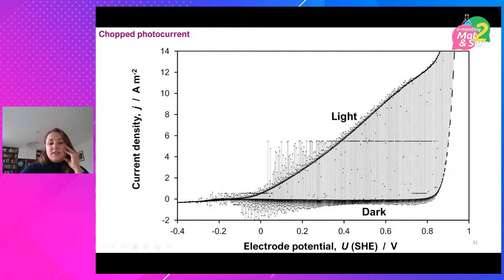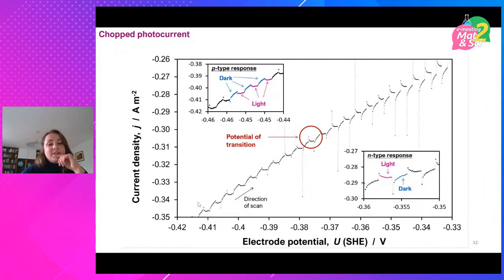And what we were quite interested to see is that apart from this main region for hematite, where we all know the photocurrent is where you expect to see it, what we also saw, if you look at what happens at about minus 0.2 volts, is that there is an additional region of photocurrent. And that's definitely anodic photocurrent. So having looked at that, we were like, okay, well, the flat band has to be negative of that. So eventually, through very laborious experiments, it's not very clear from this plot, but we found the potential of transition from cathodic photocurrent, even on hematite, very small, transitioning to anodic photocurrent. And it happened at more negative potentials than OCP values dictated or showed.